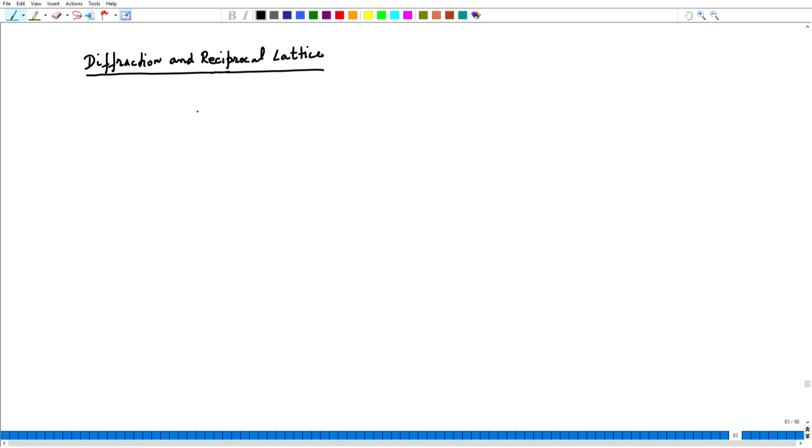So, in this Laue setup, we had set up these Laue conditions in the following way. I have some scattering point A and another scattering point B. There is an incident X-ray beam falling on these scattering points, and there is a scattered beam reflected in a certain direction. The incident beam is given by the unit vector S naught, and the scattered beam direction is given by the unit vector S.